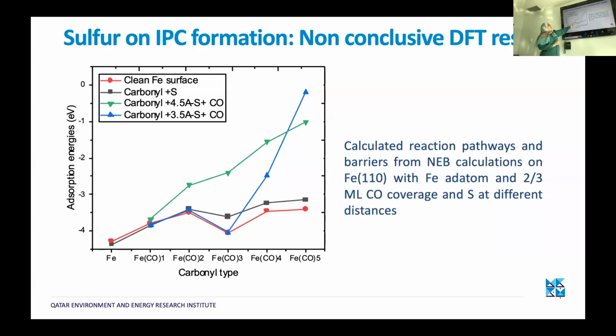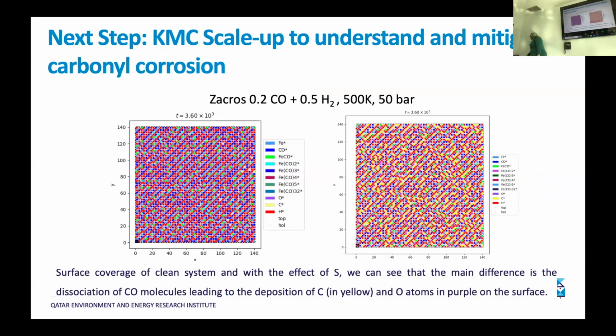And you see that, regardless of what we do, we're seeing very similar trends. So we don't see a trend that is showing that sulfur could enhance the carbonyl corrosion. So in this case, we had to go to other methods. We used kinetic Monte Carlo. We scaled up to understand how we could mitigate the carbonyl corrosion. We used a KMC code called Zacros. And the power of this is that you can simulate over a year.